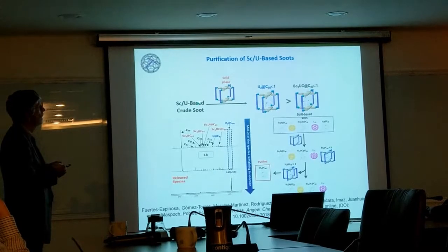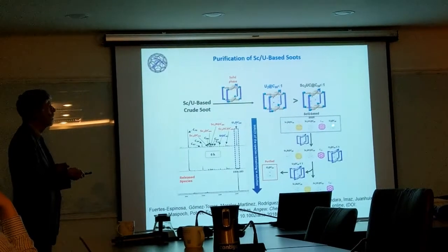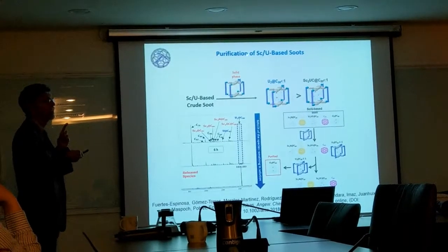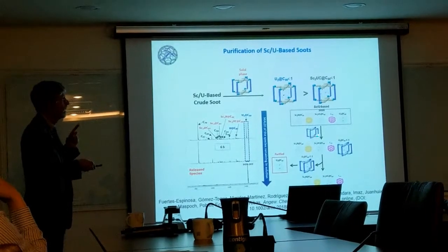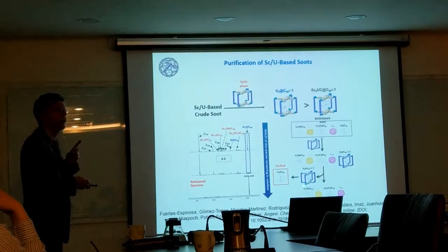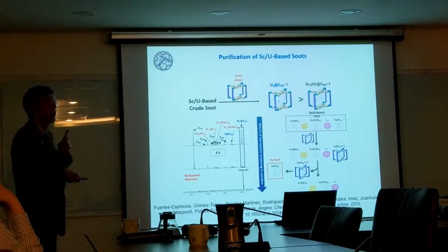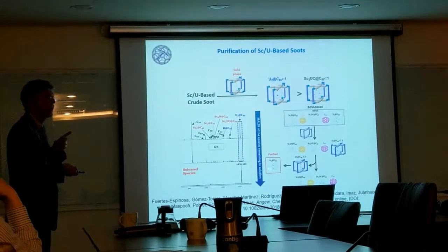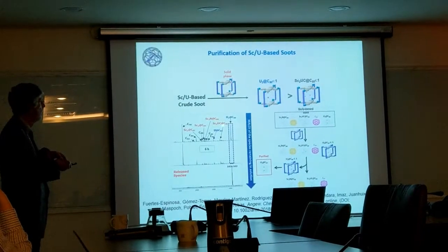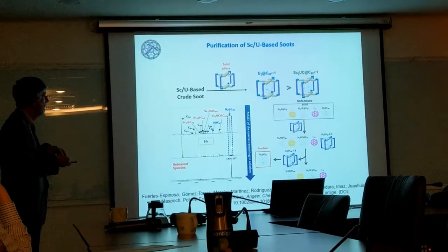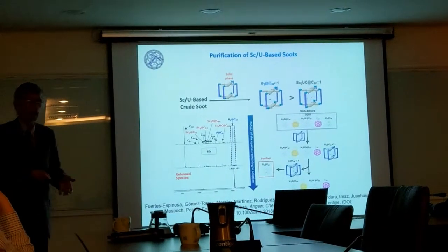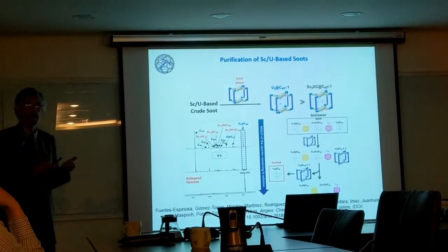As you can see from the soot, you end up with a whole bunch of different compounds. You put the capsule in the solid phase, and this is important, inside the solution containing all of these, and that solid phase is able to selectively bind only one compound, which is uranium-2 inside C80. And you can filter, and you can quantitatively separate. Look at the mass spectrum. You start with U2@C80 and all of these things, and you selectively eliminate it completely. Then, using a solvent technique, you can just release it, and you end up with pure U2@C80.